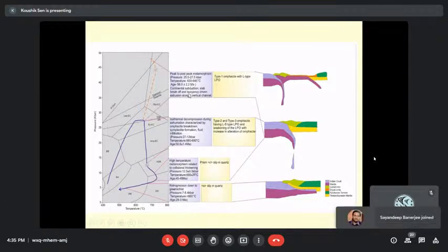Although I would like to point out that even uranium-lead zircon may not always be the ideal chronometer for metamorphic events, because how thick the rim is developed during the metamorphism is very important. So nowadays people are doing rutile and titanite and all that. Those have a closure temperature of 550 to 600, so maybe they are more reliable nowadays. But I am not aware of any such study that has been published from Tso Morari, maybe in the near future. So currently all we have is uranium-lead and argon-argon.